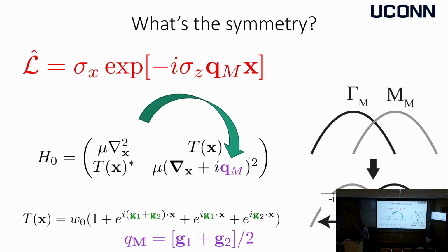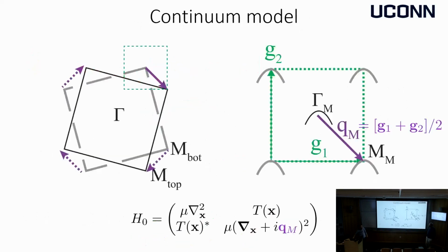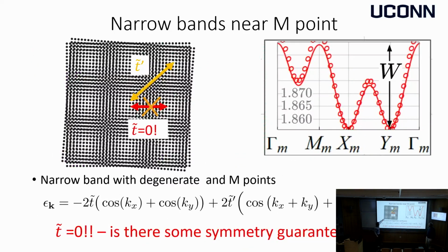There are actually other effects that are exponentially suppressed, by e to the minus 1 over theta. Microscopically, if you look closely at these two sites, they actually differ. Here, the middle of this unit cell is empty, and here you have an atom. Previously, when people studied this in tight binding models, they attributed all these effects to this actual real doubling of the period. In our continuum model, this is erased, and the effect is still there. So what we found is that those things will matter at high twist angles, but at low twist angles they are suppressed, as I said, by e to the minus 1 over theta.